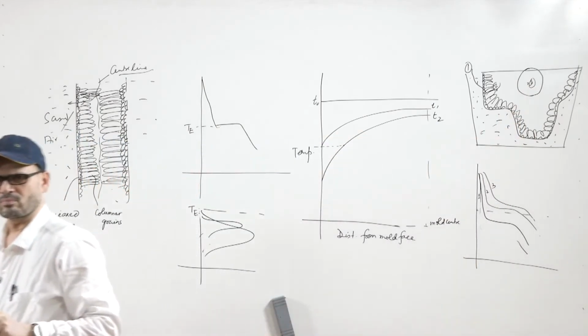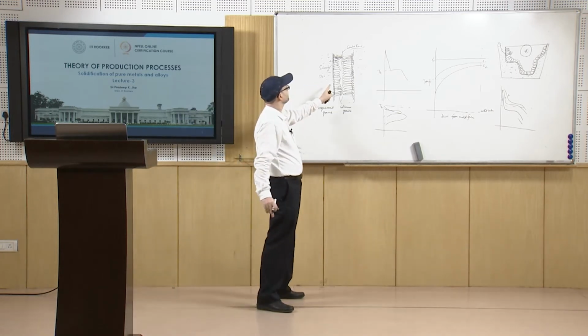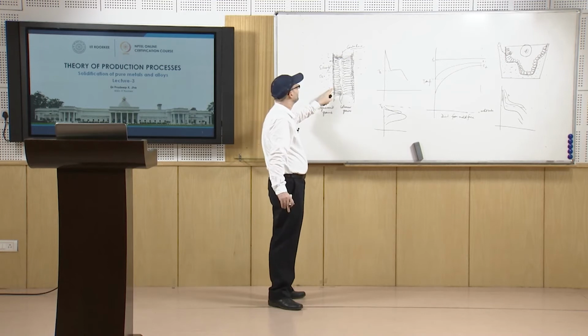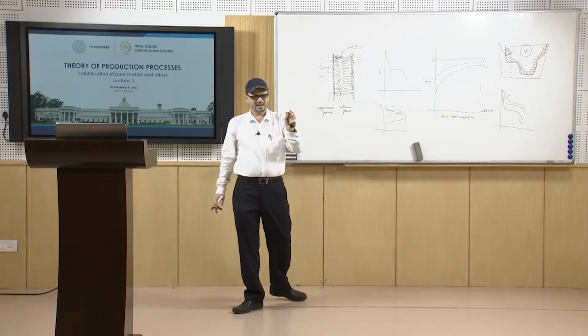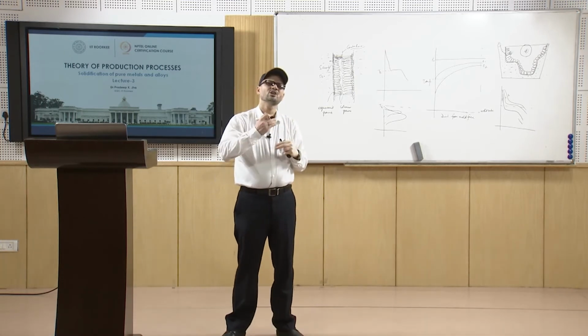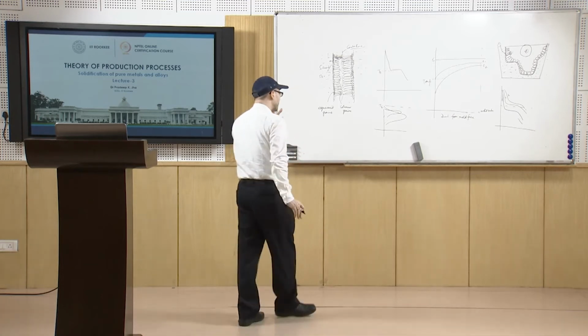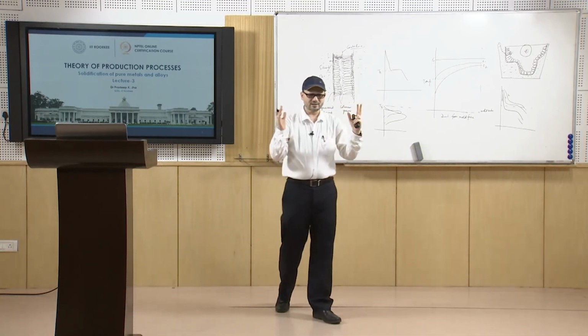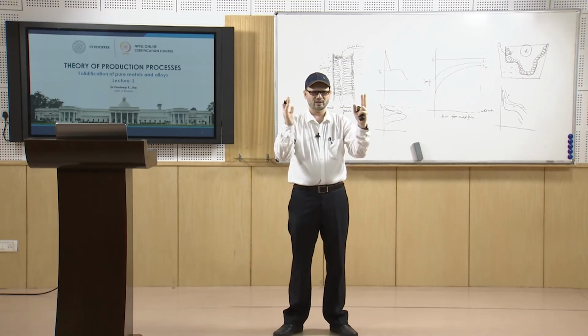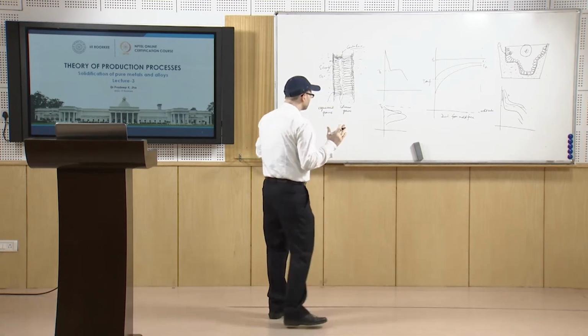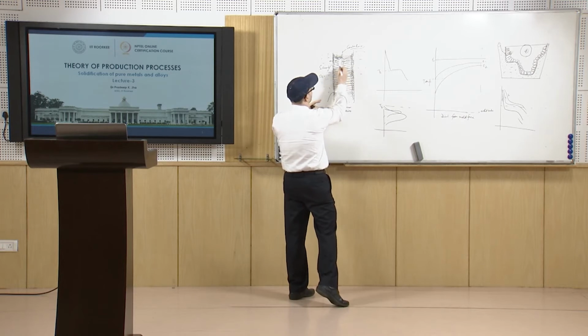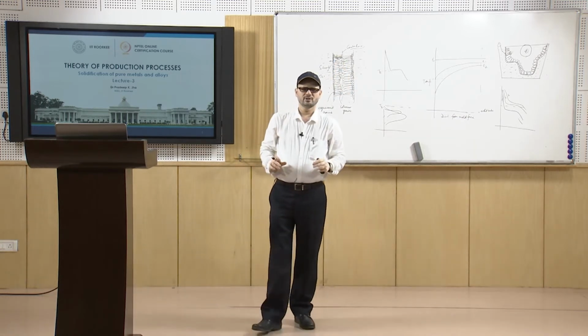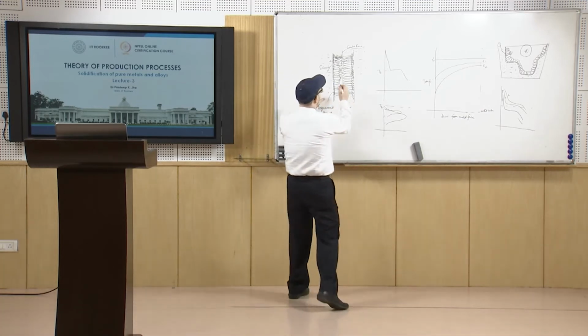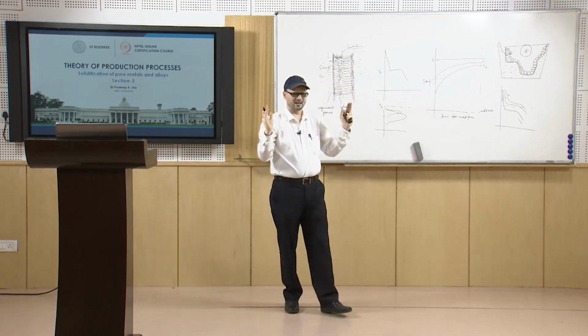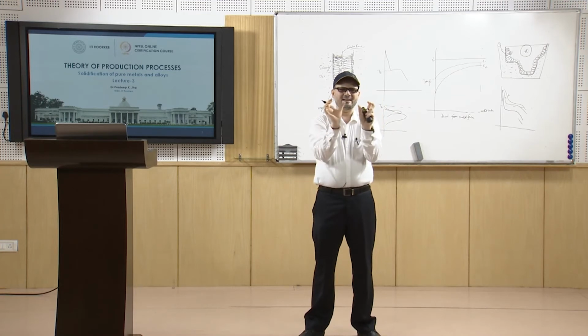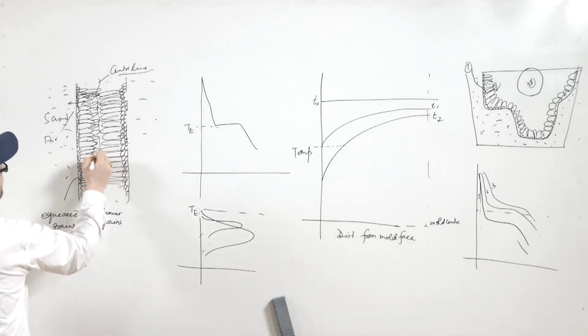So what we see now, this kind of solidification mechanism where you will have initially the formation of certain small thickness, and then this thickness further grows slowly, and this grows in a very uniform way. From both the sides the growth of these cells goes on continuously, and this growth continues till these grains meet at the center. So in this way the solidification will cease at this point, because from both the sides the solidified cells are approaching each other and they are meeting there. So this way your solidification is complete here.